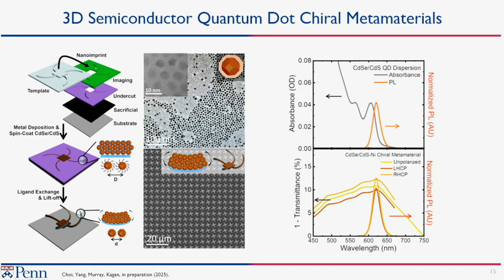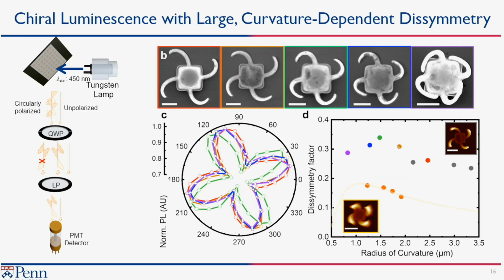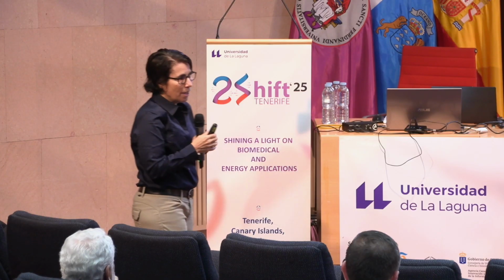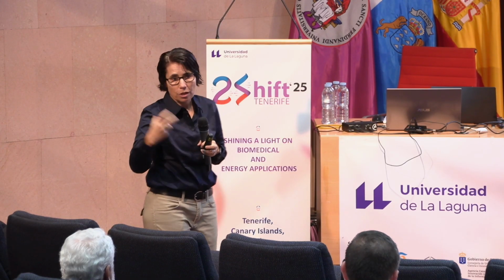If you look at the luminescence, here it compares right-hand and left-hand circularly polarized luminescence, and you can certainly see that there's a difference. We're creating some dissymmetry in the circularly polarized luminescence. To tell you where we are: we've made a lot of samples and done a lot of spectroscopy. In this case, I'm only going to tell you about some spatially resolved spectroscopy we did to try to understand these processes. We illuminate these materials with unpolarized light and then characterize how circularly polarized the luminescence is. That's just like the two spectra I showed you before, but we can also control the curvature of these materials. Each one represents one building block in a very large array, like I've showed you before, and we can make many samples where we control the curvature or folding of these structures.